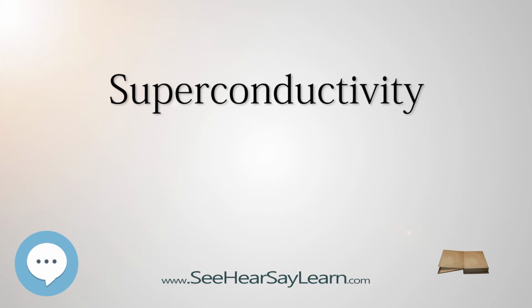In 1962, Josephson made the important theoretical prediction that a supercurrent can flow between two pieces of superconductor separated by a thin layer of insulator. This phenomenon, now called the Josephson effect, is exploited by superconducting devices such as SQUIDs. It is used in the most accurate available measurements of the magnetic flux quantum Φ0 = h/2e, where h is the Planck constant. Coupled with the quantum Hall resistivity, this leads to a precise measurement of the Planck constant. Josephson was awarded the Nobel Prize for this work in 1973.